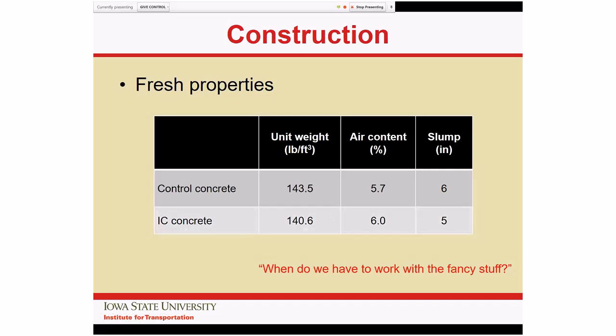And as I said, we ran with a water cement ratio of 0.45 to be the sweet spot between: if it's too high, we don't get mechanical performance. If it's too low, the shrinkage risk seems to go up fairly quickly. So again, thanks to some help and support from University of Ohio, who sent a team out, we measured the unit weight, and again, the control mix was about 3 to 5 pounds heavier than the internally cured system, and that's to be expected. The air content was pretty close. The slump was in the 5 to 6 inch range.